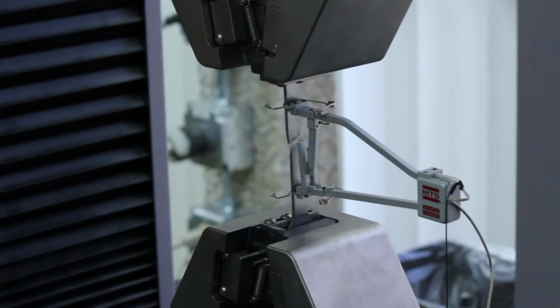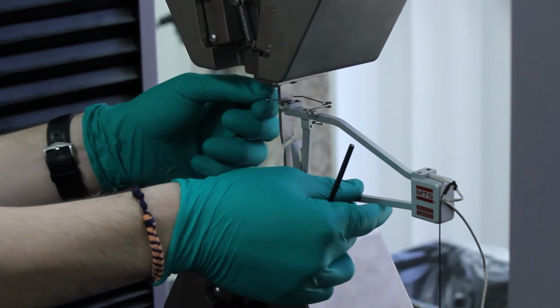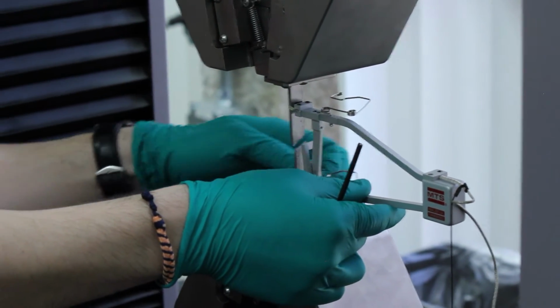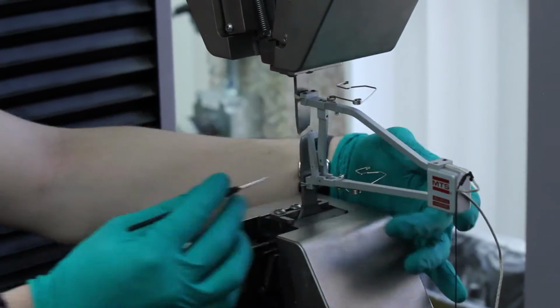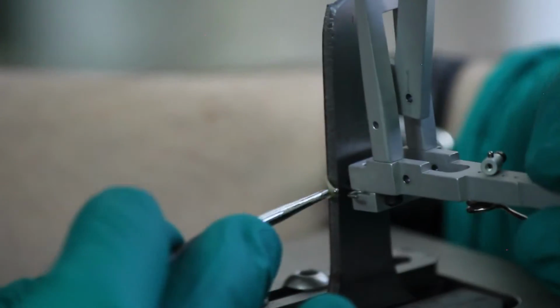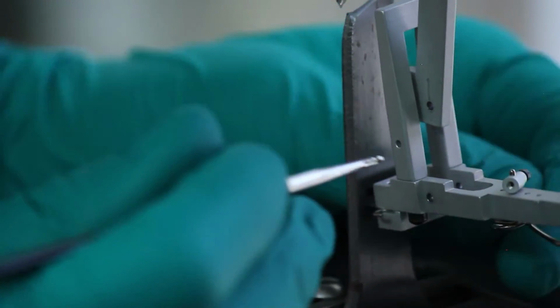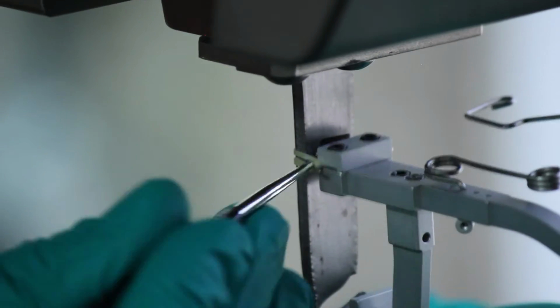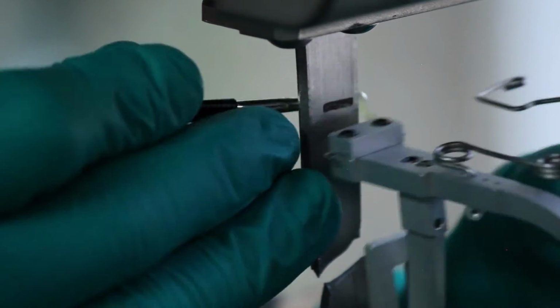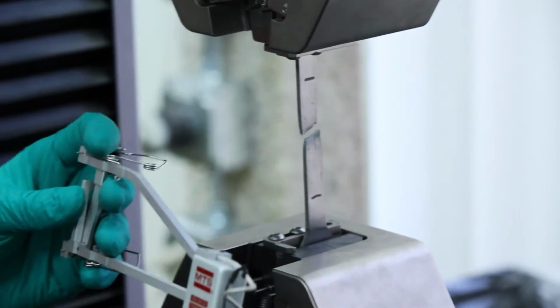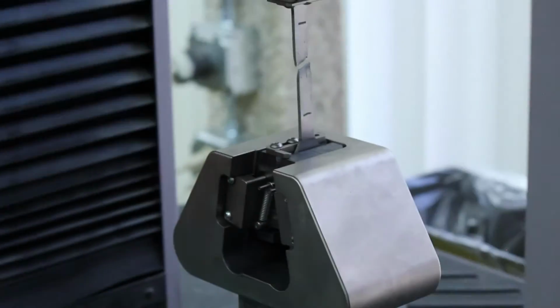Once the test is complete, you will remove your sample from the tensile tester by first undoing the metal retention clasps and then removing the rubber bands you put on earlier. Once you remove the extensometer from your sample, reinsert the retaining pin into the extensometer.